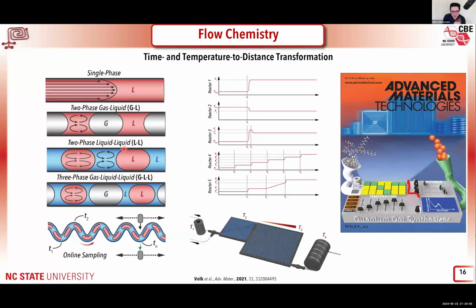Now, in addition to time to distance transformation, you also have temperature to distance transformation. The different positions along your reactor actually correspond to different temperatures. So you can have these heating plates, and you can put your flow reactor, in this case just Teflon tubing, inside your heating plate. And you can have different temperatures or temperature profiles for each plate. So you can have these tunable heating profiles that are impossible to have in a batch reactor. And you can heat and cool down your reactors at a rate of 400 degrees Celsius per second, which is again impossible to have in a batch reactor. So in a sense, we have all these knobs to control all of these processing parameters. You have this precise control over all of the processing parameters of your material synthesis through these flow reactors.